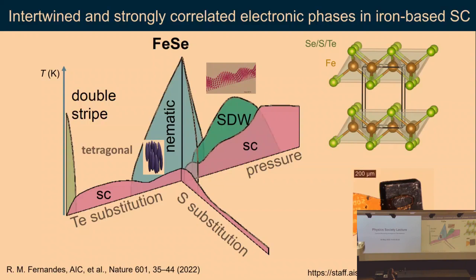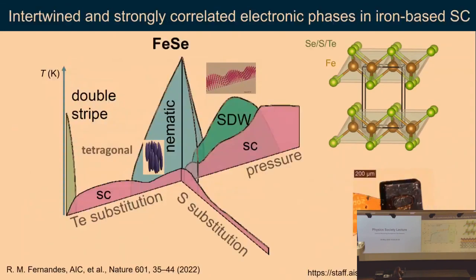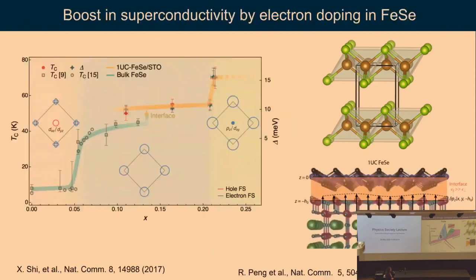And to do all these studies, one needs to have access to very, very clean materials. This is a picture of almost perfect single crystals of iron selenium sulfur, which has very nice edges, and it shows this tetragonal symmetry. Another thing about iron selenium, these are all bulk materials. They are single crystals. One can grow them in the lab using a technique called chemical vapor transport.